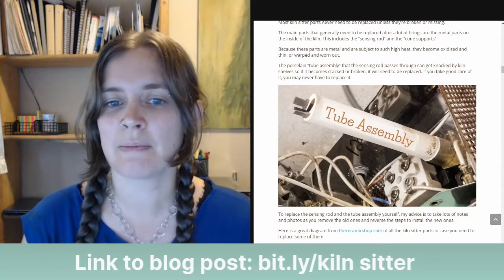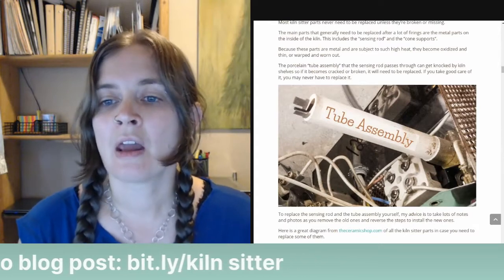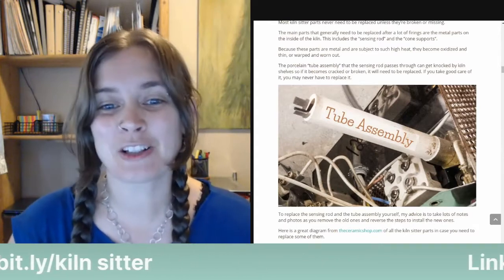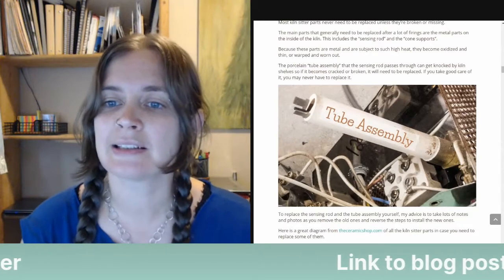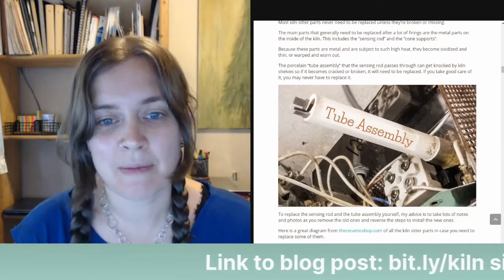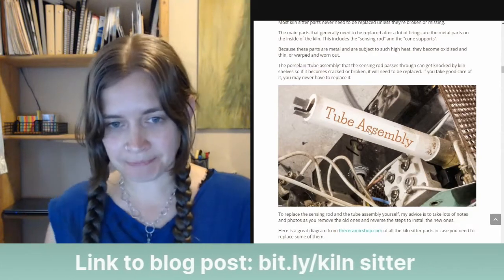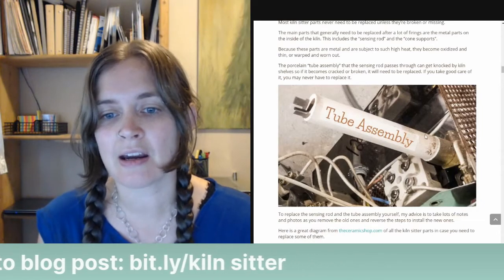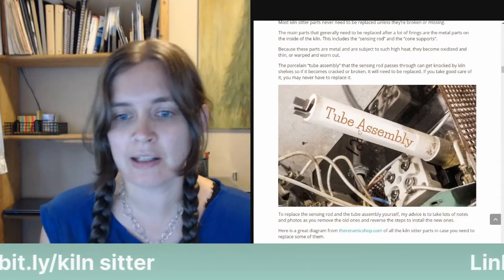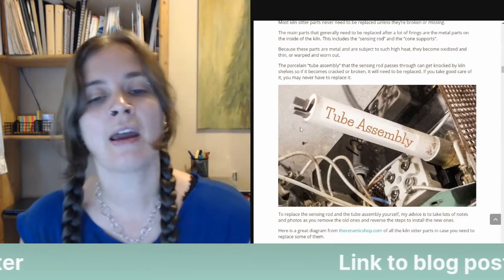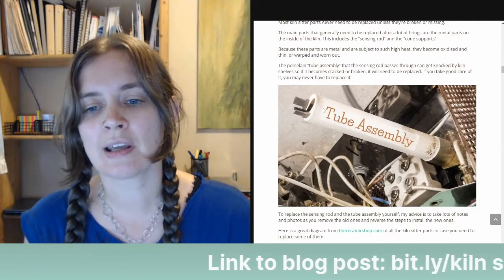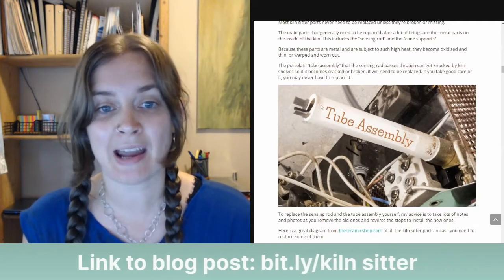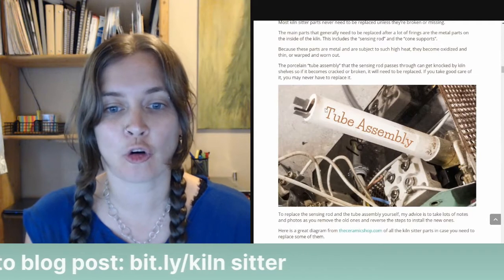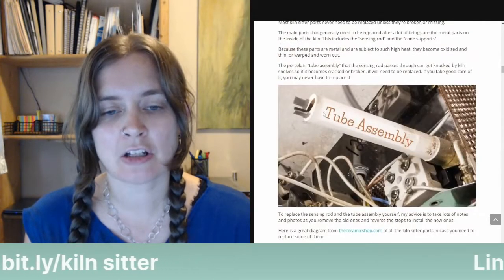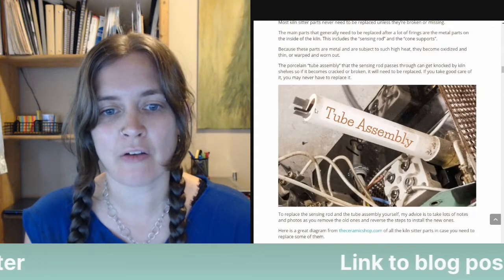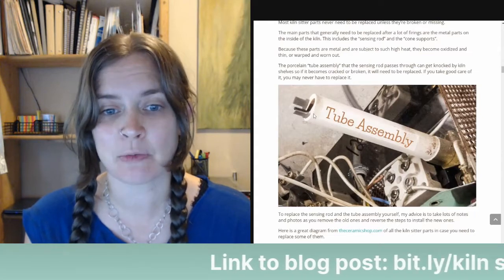so it becomes cracked or broken. So if it becomes cracked or broken, it will need to be replaced. If you take good care of it, you may never have to replace it. So this tube assembly here is what goes from the outside of the kiln into the inside of the kiln. And it is made of porcelain, and it can break, it can chip and crack. So you want to just make sure as you're loading your kiln that you avoid hitting this with your kiln shelves.